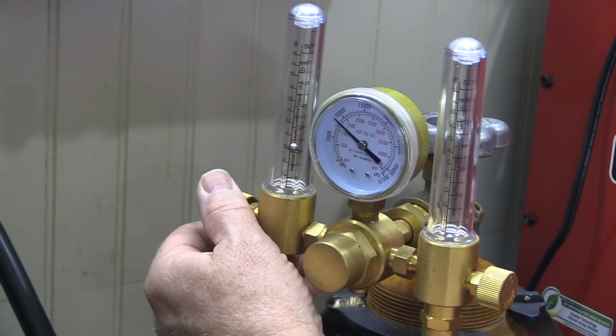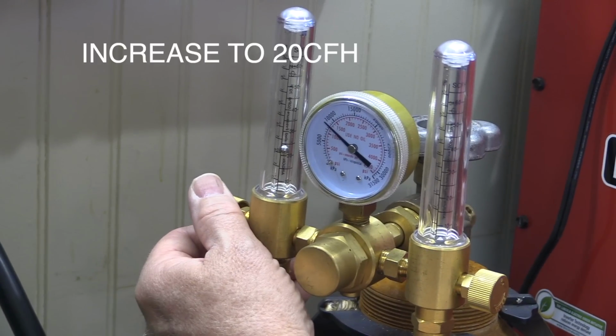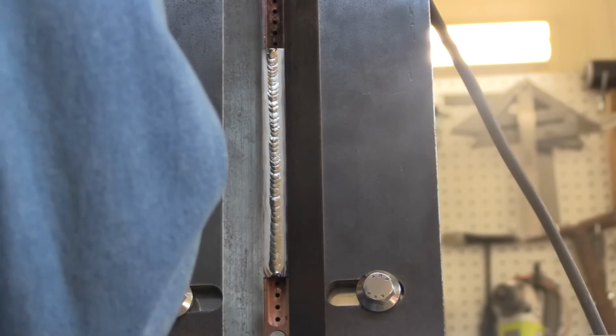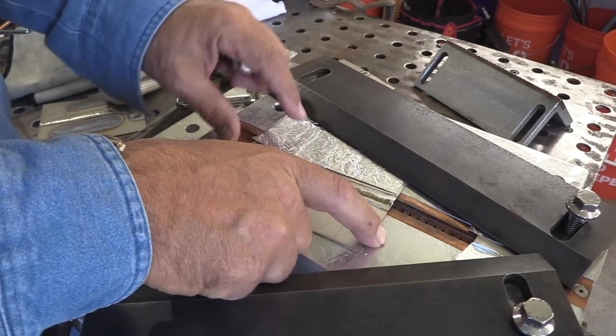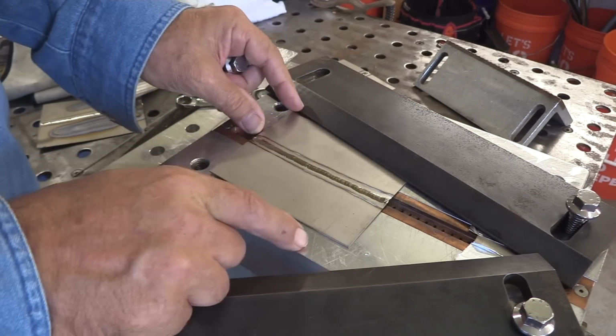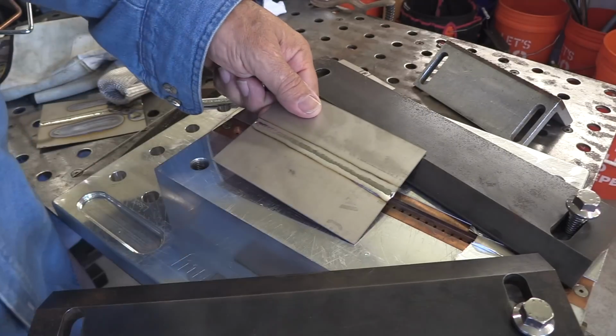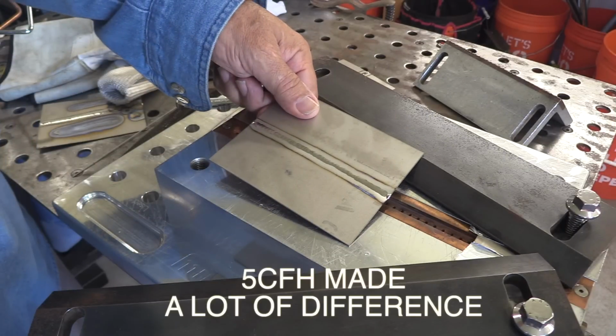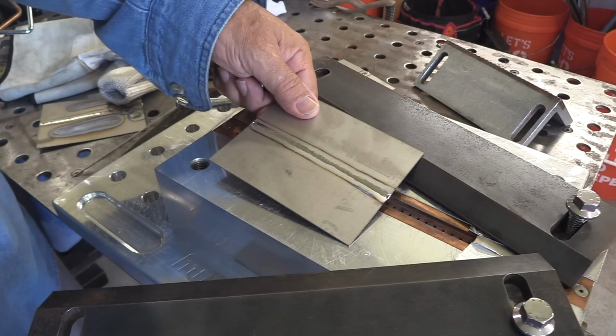I'm going to bump the argon flow up just by 5 CFH, see if we can improve the discoloration on that root. Let's do it. I'm going to bump up the fixture purge by only 5 CFH to 20 CFH, and we'll check it out and see if that does a better job. I have had some fixtures, some small fixtures, where it only required even 5 to 10 CFH for a good purge, but this one's pretty large, so 5 CFH more made the difference.